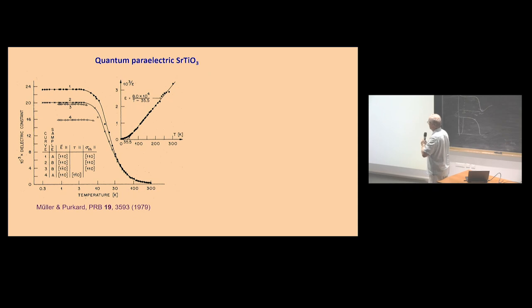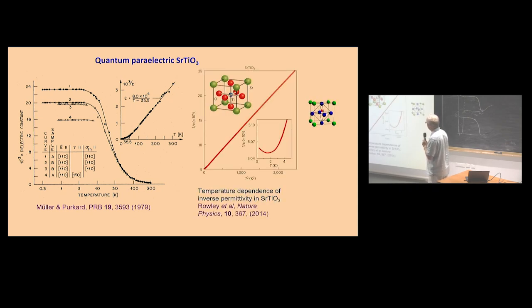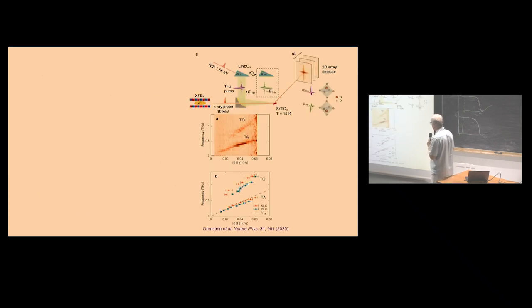Okay, one explanation was quantum fluctuations, but interestingly, at low temperatures there is a tiny peak, which is not quite clearly seen here, but if you plot reciprocal permittivity, there will be some minimum at 2 Kelvin. It means a maximum here. And the question is, where is it coming from? Yeah, this effect. And a very recent paper from this year